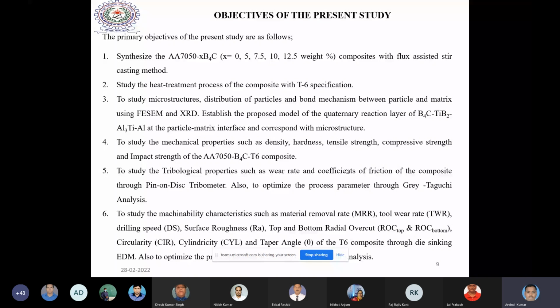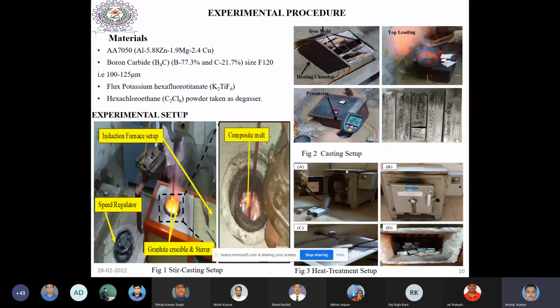So basically, this was the experimental setup which I have used. I have used aluminum alloy 7050. Here, the major alloying element is zinc, that is 5.88. Other things as well. And boron carbide I have used, with size 100 to 125 micrometer. I have used the flux assisted stir casting method. The flux was K2TiF6, that is potassium hexafluorotitanate, and one degasser I have used, that is hexachloroethane.